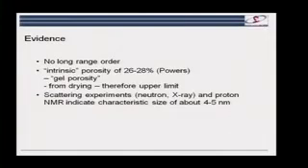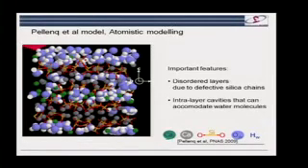not only are you losing the water between the particles, which we're going to talk about in a minute, but we're also losing water from within the layers. We talked back here about this model where you could have water in the layers. It's quite clear that in Powers' experiment he was drying so severely that water was coming out of these layers. But nevertheless, you have this point that as you form more and more CSH, you get more and more of these pores in a small region.